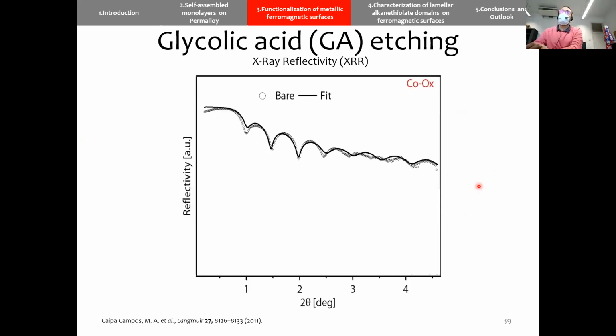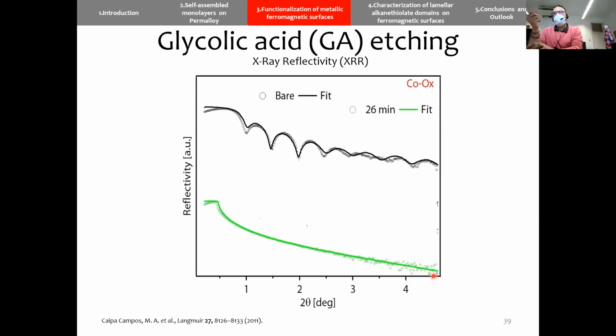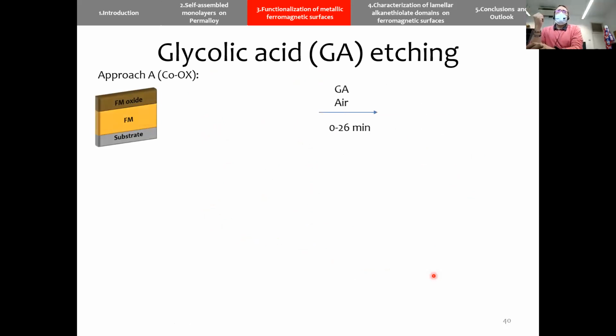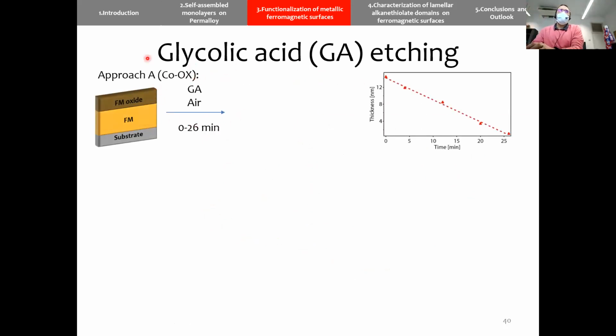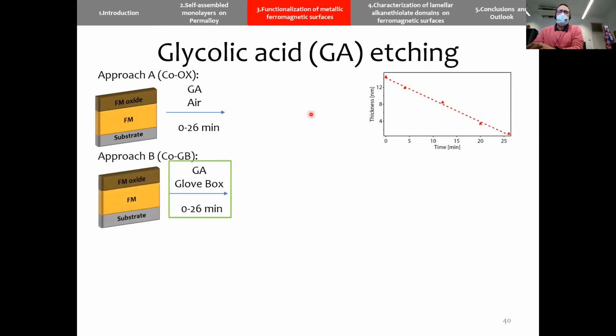So if we take cobalt and we do our fit, and then we expose it to this glycolic acid for 26 minutes in air, we observe that all the fringes are gone. This is the characteristic signal of a silicon substrate with nothing on top. So we observe this, and then we started thinking about what was happening. In this case, as I said, we exposed to air, we did a kinetic, and we observed that over the course of 26 minutes, we were losing some material. This is the thickness from the adjustment of the XRR.